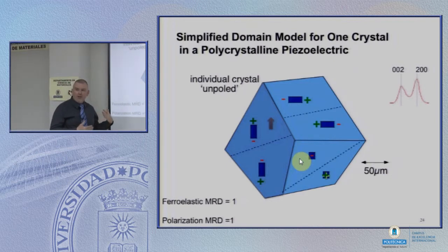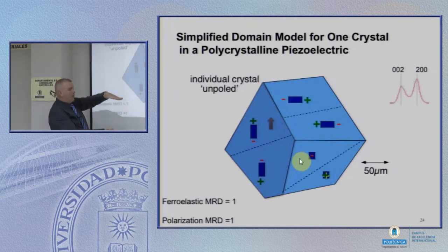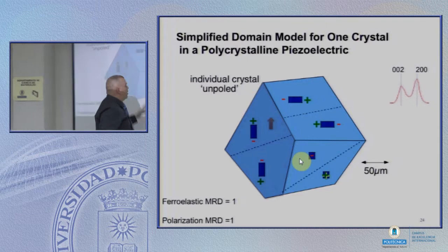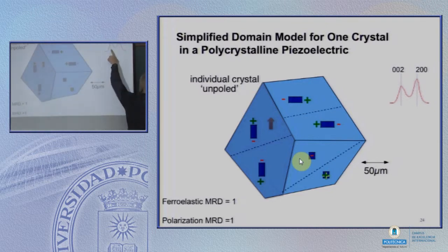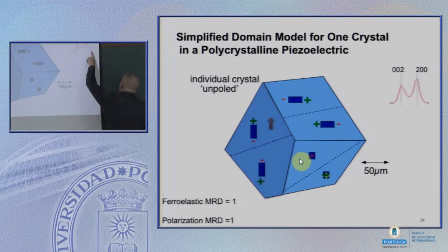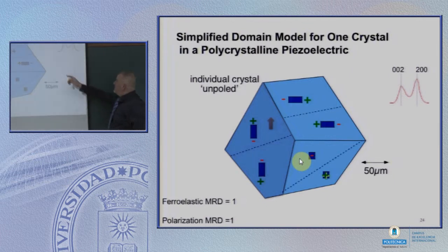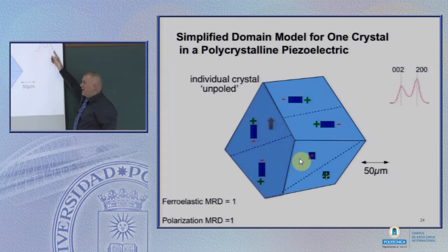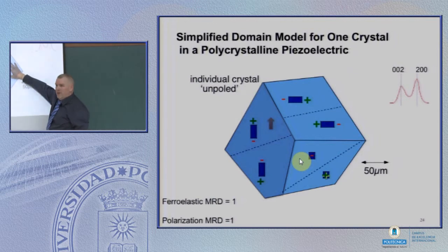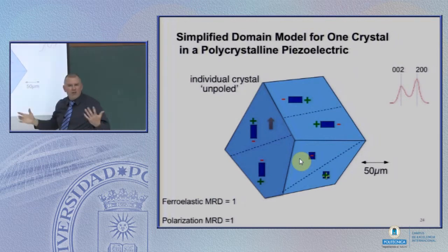We do X-ray diffraction. Most of the time we're doing X-ray diffraction with our samples horizontal. So if this is the prototype for these types of orientations, what we would see in X-ray diffraction for the 002 peak, which is an allowed reflection, and the 200 peak is that this peak is about half of that one, right? And that's because there's twice as much of these two, ones with a short dimension here, as there is of this, right? And so that's what we see.